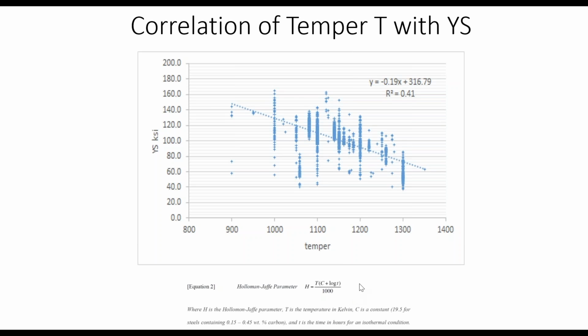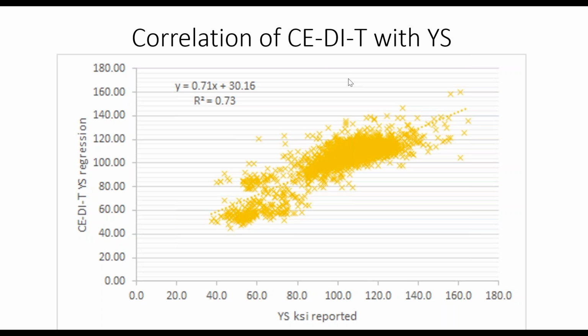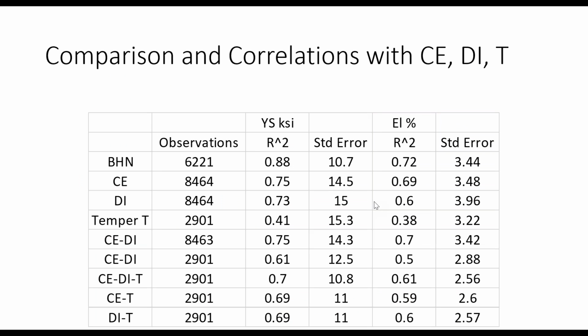So the Hollomon-Jaffe parameter was developed for tempering response for heat-treated steels. If I include carbon equivalent, DI, and temperature, I don't change the correlation very much, but I get a fairly nice regression with that. You can see the carbon steel, and here all of the alloy steels fall pretty closely with each other. So I can look at all of that data pretty quickly.